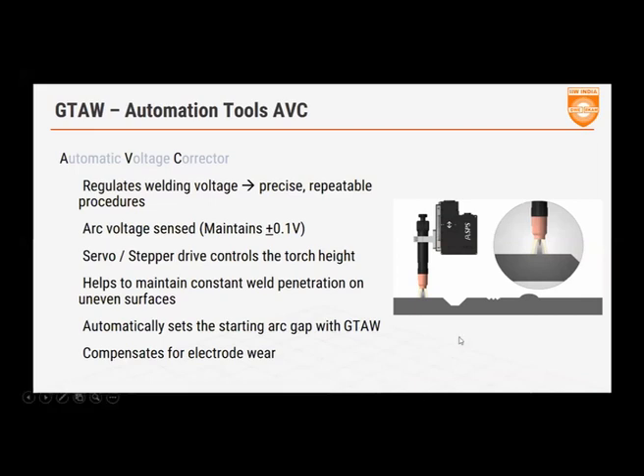Now what happens is, typically when you have a lot of ovality as we were sharing, or you have uneven surfaces, the distance between your torch and your job would change. Now you see here, while you go through it, it's changing the distance. Now what happens is we measure the voltage very closely. Now those who know, what happens when you move a torch closer to the job, your voltage reduces. And when you take the torch away from the job or the distance increases, your voltage increases.